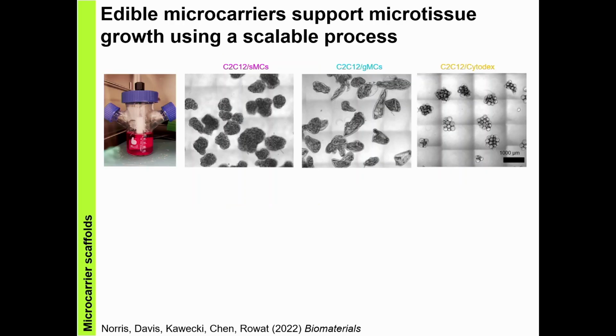So you might have noticed that these cells and microcarriers are forming aggregates, and this is something that was very evident in culture with the C2C12 cells that we were using for proof of concept on the spherical and grooved microcarriers, also the Cytodex beads, and this had been observed before, but because we're able to make the microcarriers out of edible materials, this enabled us to simply harvest these aggregates to form a meat kind of patty.